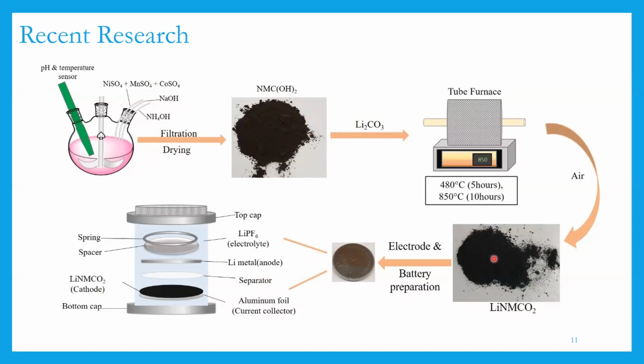When performing electrochemical analysis, you take this powder, make a slurry, paste it, and coat it on a current collector, which is aluminum foil. This is battery grade aluminum foil. And then you use lithium metal as your anode.